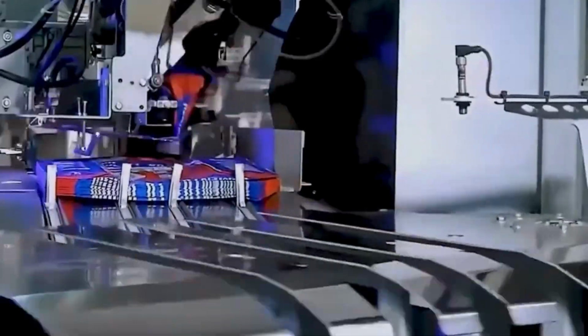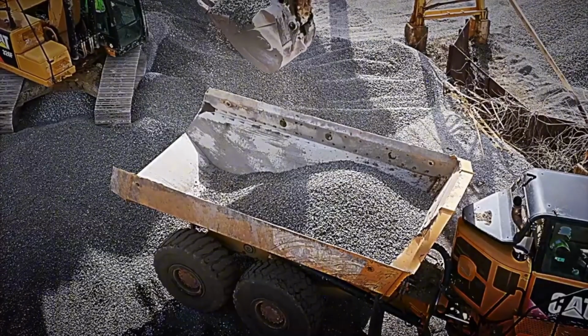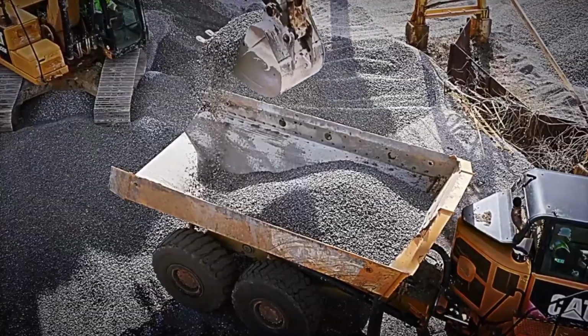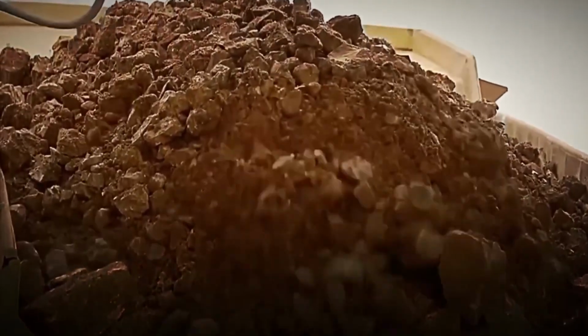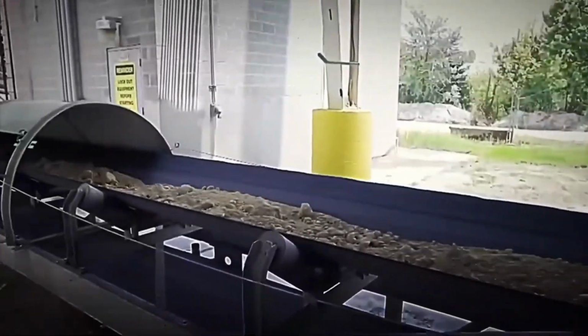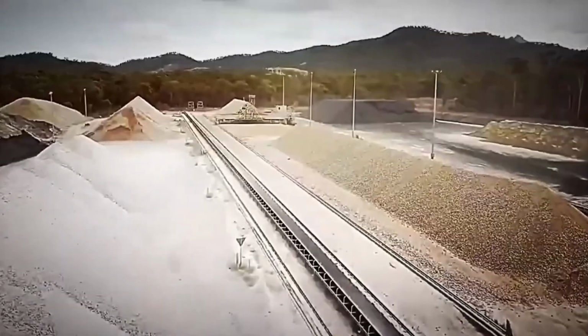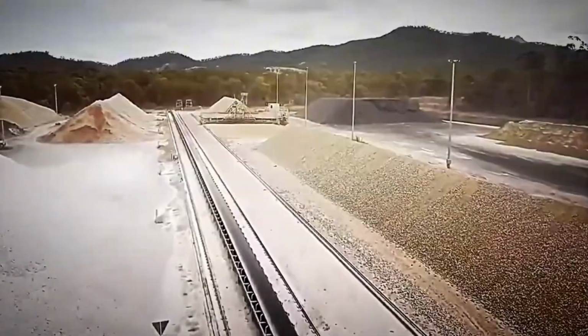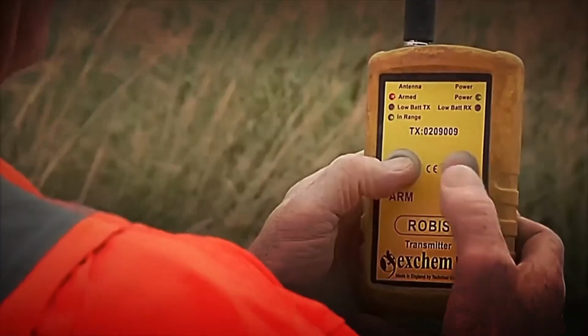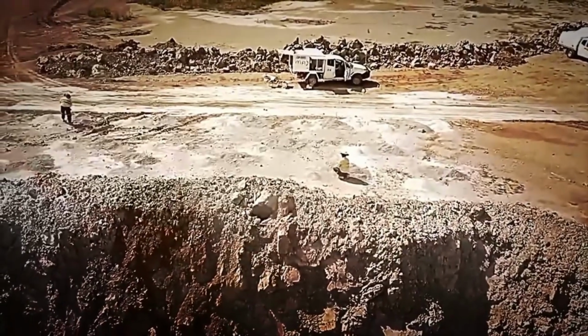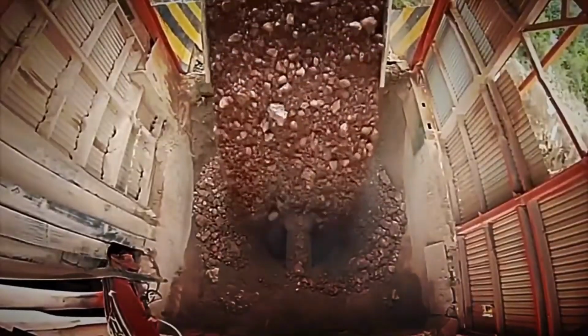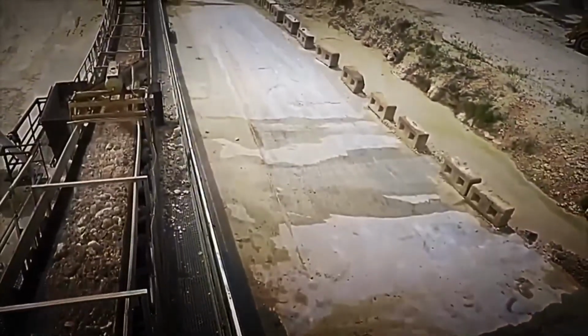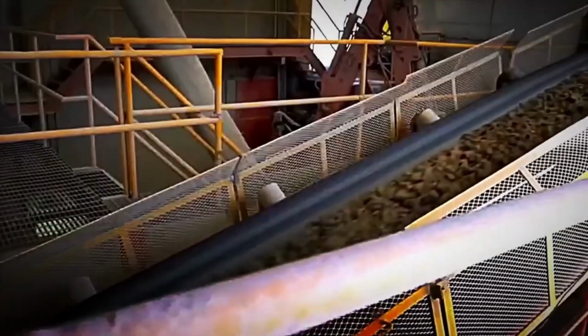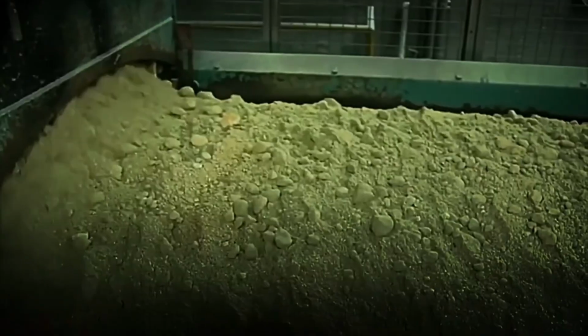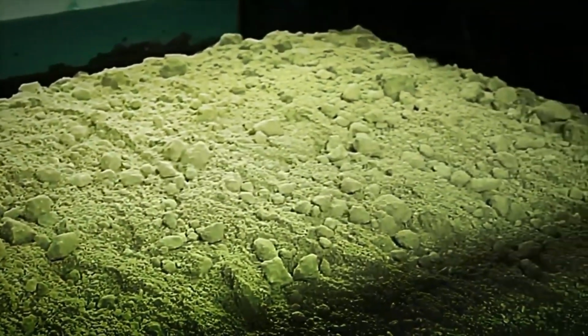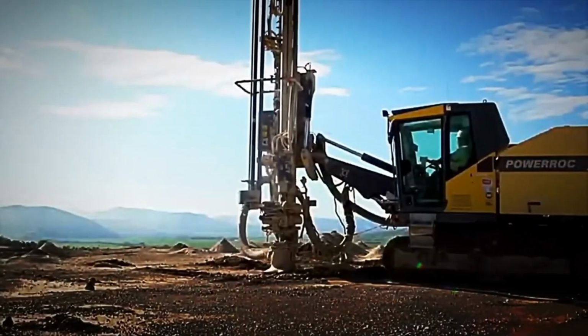Throughout the entire cement-making process, quality control is constant. Laboratories test raw materials, raw meal, clinker, and finished cement for chemical composition, particle size, setting times, strength development, and impurity levels. X-ray fluorescence spectrometers provide instant chemical analysis. Strength samples are cast into test cubes and crushed by hydraulic presses after 1, 7, and 28 days to measure performance. If results drift from specification, operators adjust mill settings, raw mix proportions, or kiln parameters to correct the process.